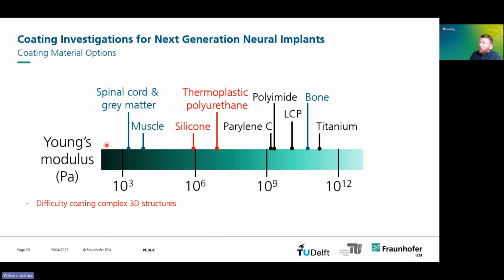Now, while we really like this TPU process, there is one major difficulty with both this process and several other processes that are deposited using solution. And this is a difficulty coating complex 3D structures. So a solution for this is to use medical grade Parylene C. This is compatible with microfabrication and has long been used since the 80s, and it's deposited via vapor deposition, which is a different method.